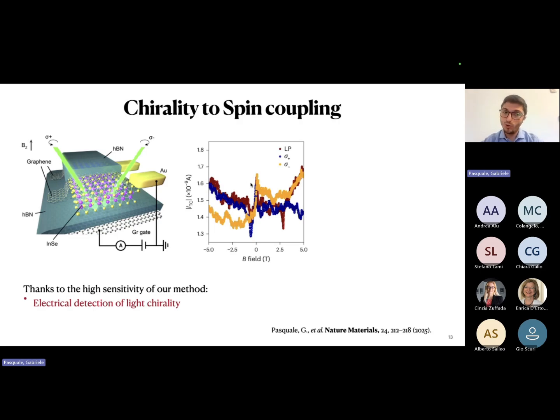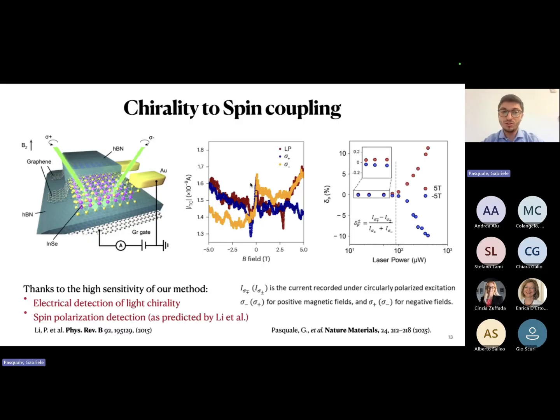And the point is that not only could we do this electrical detection, but we could use this to demonstrate a spin polarization detection in a flatband semiconductor, which was predicted around 10 years ago, and really remained elusive for a long time because of the very tiny magnitude of this effect, which is extremely hard to detect. And this tool, this method really provided us the opportunity to detect this spin polarization in the system.